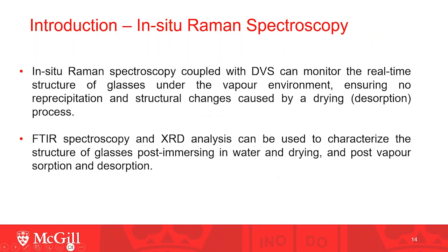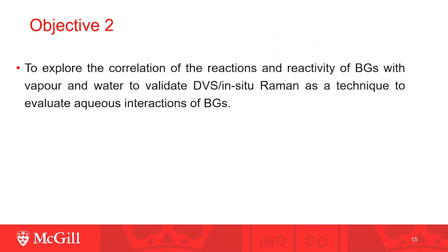Moreover, in situ Raman coupled with DVS can monitor the real-time structure of glasses under vapor environment, avoiding the structural change caused by a drying process — compared to FTIR and XRD analysis, which can only be used to analyze the structure of glasses exposed to aqueous environment and then dried. Therefore, our second objective is to explore the correlation of reaction and reactivity of borate glasses with vapor and water, in order to validate DVS with in situ Raman as a technique to evaluate aqueous interactions of borate glasses.